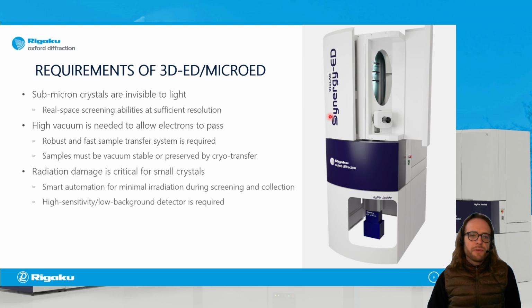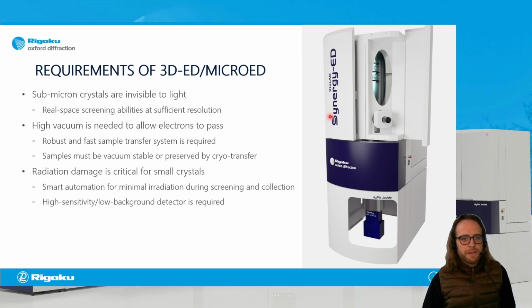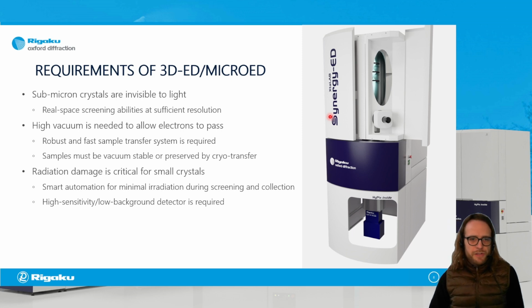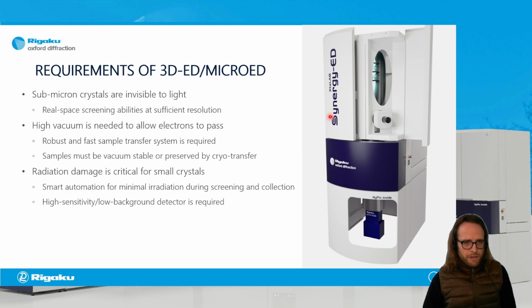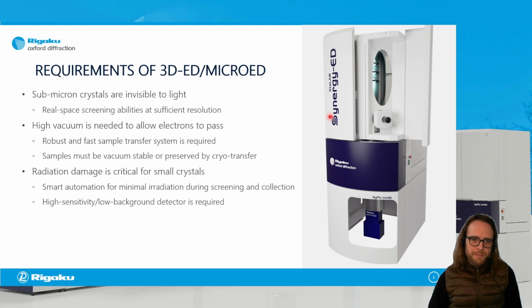Another aspect that's important is radiation damage. As I mentioned before, electrons are quite gentle with any sort of matter, but still you need to extract a lot of information from a very small diffracting volume, so you need a very good level of automation to minimize any irradiation during screening and actual data collection. And even more importantly, you need the detector with the highest sensitivity you can get your hands on, not to waste a single electron on background noise.